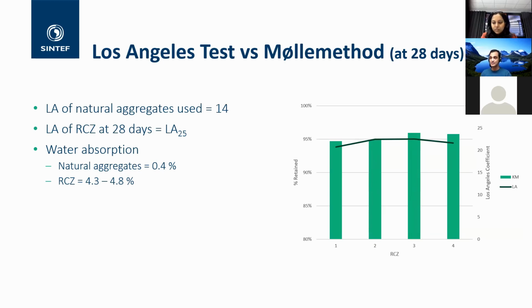So we used this method, and at 28 days we again did this modified Molle method, and we tested the same aggregates with the Los Angeles method, because at 28 days they were hard enough to handle all the stresses of the Los Angeles test. On this plot on the right, I plotted the Los Angeles values as a line graph, and the bars are the results from the modified Molle method. And the 4 curves are 4 different cycles for these RCZ aggregates. And again, we see a very good correlation between these 2 methods, suggesting the test method that we used is working very well. And the Los Angeles method was not working for aggregates at the early stage of life, which was too harsh, but it's working at 28 days.